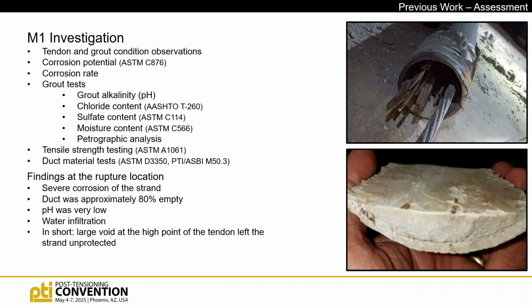That lower image is really key here. That is a piece of grout that we found on the floor at the rupture location. You notice it's got the top level surface there. That was the top of the grout that was in the duct. And you barely see an impression of a wire in it. The tendon was completely unprotected. It was in a void through the high point of that deviation. It had leaks in that diaphragm, so the pH was very low due to chlorides coming in with the water recharge.